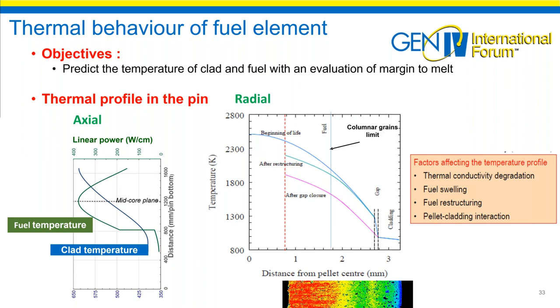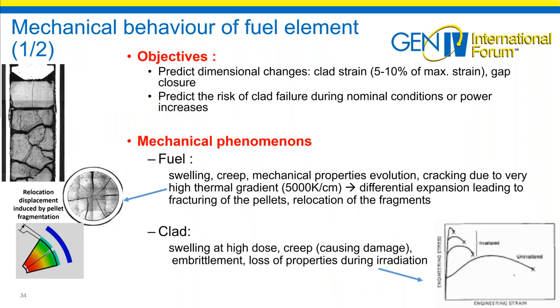So these temperatures decrease after some days. We start with the blue curve. After the opening of the central hole, we have the green curve with the temperature lower by about 300 degrees. When the gap is closed, the temperature is even lower. It's the pink curve. So the safety analysis with the evaluation of the margin to melt is achieved all along the irradiation, but the highest temperature is reached during the beginning of the irradiation. This is an advantage because the thermal conductivity is not yet affected by the irradiation, so the uncertainties on the properties are the lowest. So next slide, please, on the mechanical behavior of the fuel element.